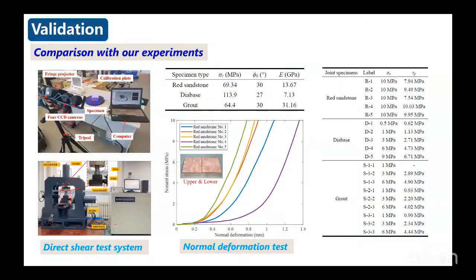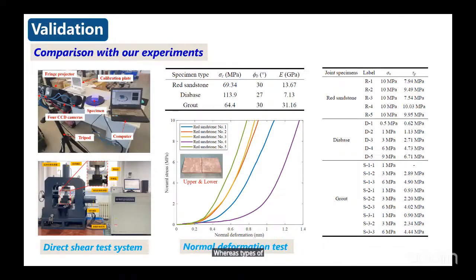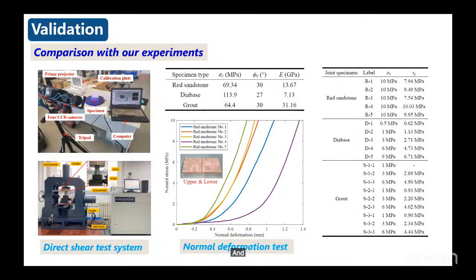To validate the proposed peak shear strength criterion, we conducted in-house experiments, including both the normal deformation test and the direct shear test on various types of rock joints using our direct shear test machine in our laboratory, containing both natural rock joints, namely the red sandstone joints, the diabase joint, and artificially made rock joints, synthetic joints made of grout. And we applied low to high normal stresses to obtain a very diverse range of the peak shear strength.